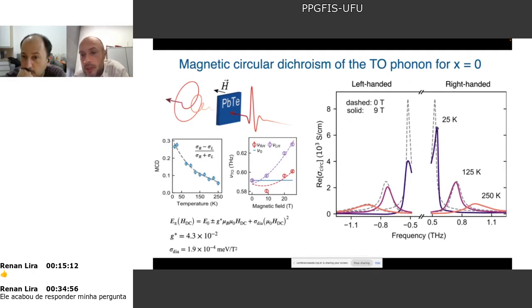If we plot this phonon frequency as a function of magnetic field, you can see here, this is left-handed and this is right-handed. You can see that there is some splitting, as in the first paper that I showed you in the introduction. And we can fit these points with this equation. One part depends linearly on the magnetic field. One part depends on the square of the magnetic field. This is the phonon magnetic moment in units of the Bohr magneton, right?